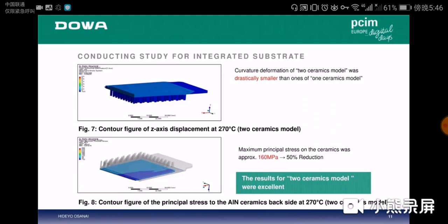Figure 7 shows a contour figure of the z-axis deformation of the two-ceramics model at 270 degrees Celsius. The warpage has been dramatically reduced. Figure 8 shows the stress in the ceramic layer, which reduced to 160 megapascals, a 50% reduction against the first model. Since the results of the two-ceramics model were excellent, we decided to proceed to the next step.